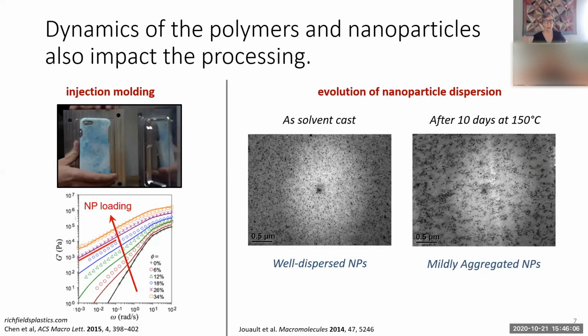And in a related topic, during that injection molding process, when it's at that elevated temperature, the nanoparticles are likely to diffuse. And during that thermal injection molding at high temperature, you can also change the particle distribution. So the way the particles are distributed in the polymer matrix is critical for properties. And so this is just an example from Sanat Kumar's group where it's solvent cast, it's pretty well dispersed, and then they anneal it at a modest temperature for a long time, and now you actually start to build these aggregates, right? And so these are the sorts of things that motivate our study of focusing on the dynamics, the polymer dynamics and the particle dynamics in this wide variety of materials.